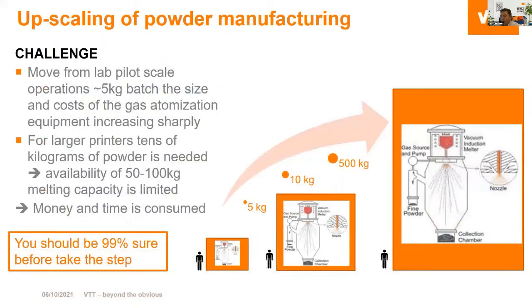Then if we think about today's topic, what is the meaning of moving from the lab to engineering, I think that in additive manufacturing and the powder route, the first challenge is connected to moving from laboratory pilot scale operations, where the batch size in our case is approximately 5 kilograms. If you would like to move to bigger batches, which are needed in larger additive manufacturing equipment, typically if you go to, let's say, an industrial size printer, you will need at least 50 to 100 kilograms of powder. And to get that powder batch somewhere is really limited.